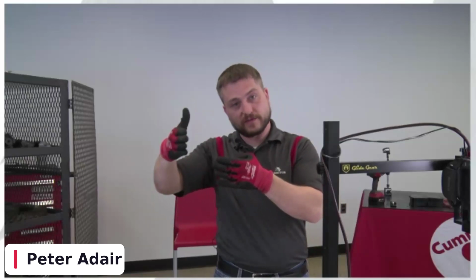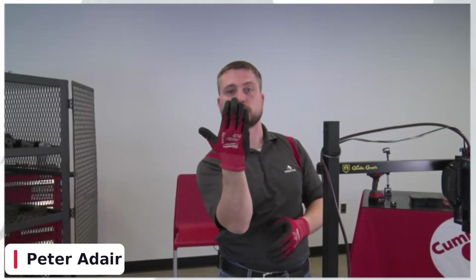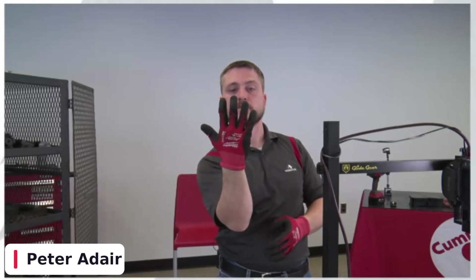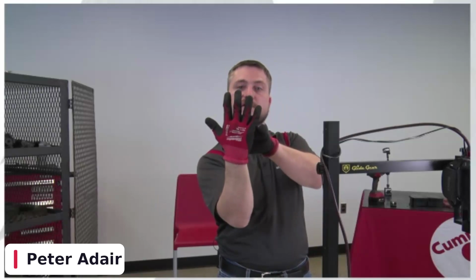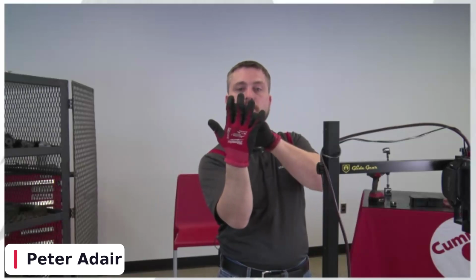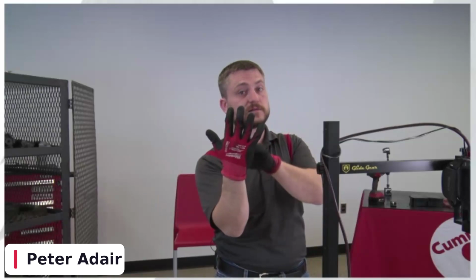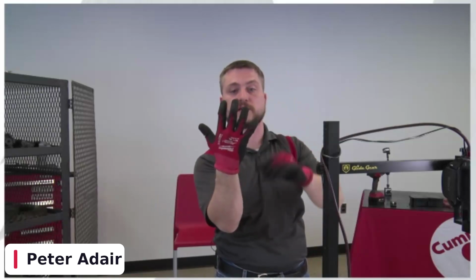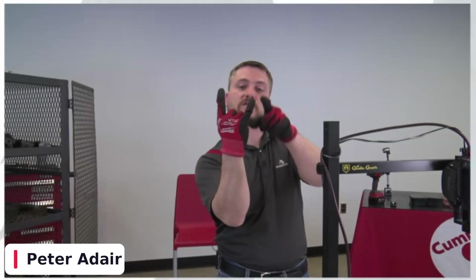So cycles versus load. When we're looking at beach marks, the tighter they are together, the closer they are, right? So in this instance, let's say we're like that. We're close together. That means I have a lot of cycles. I'm overloading for sure, but not severely. I'm getting very close beach marks, versus beach marks that look like this, where I have a large gap between them. That means I'm severely overloading and I'm not getting as many rotations or cycles through the system.